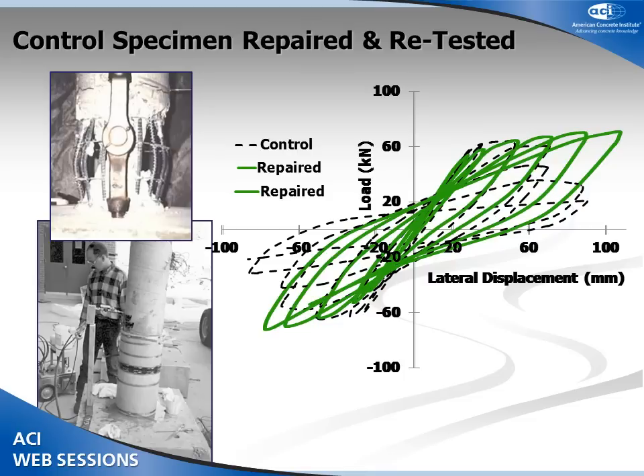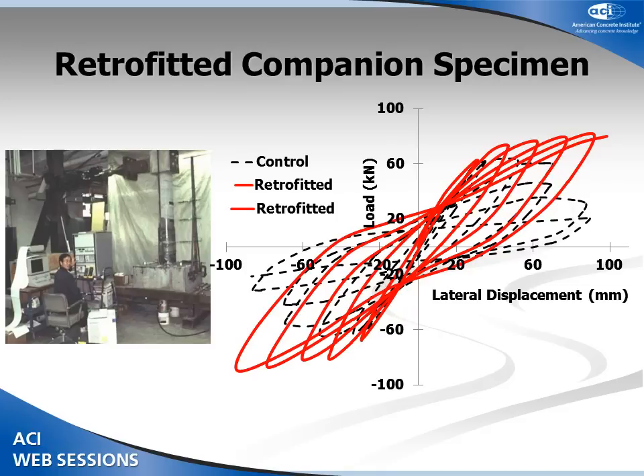The damaged column was then repaired and retested. He did not have time to clarify exactly how he repaired the buckled rebar; his notes suggest it was simply filled with concrete and then FRP was applied. If that is the case, he did get really superior behavior — quite a ductile performance after repairing the column with buckled bars. This is the comparison of controlled versus repaired. These columns are about 2.5 meters, so yield corresponds to approximately 1% drift. In the original control specimen he was not able to go beyond 2% drift, whereas in the repaired one he went up to 4% and then ran out of stroke on his actuators, implying there's more reserved strength and ductility. He also retrofitted companion specimens — the same laminates applied on undamaged columns — and got similarly good behavior.